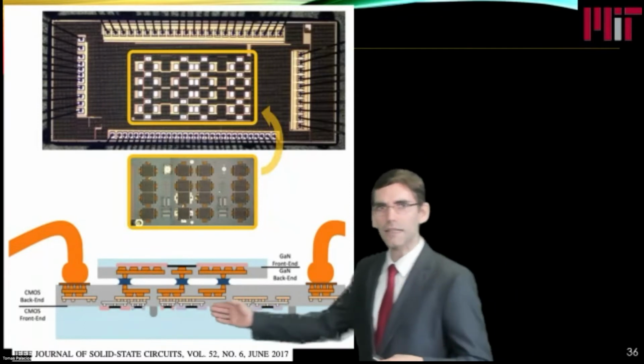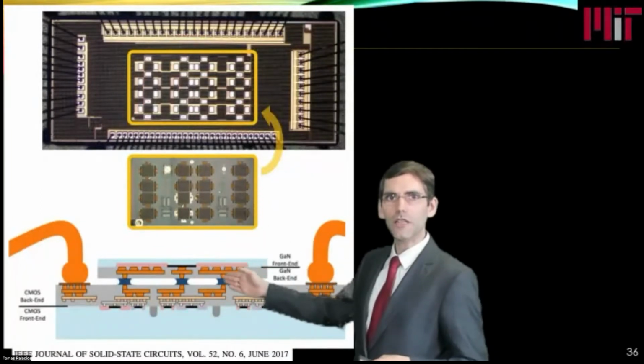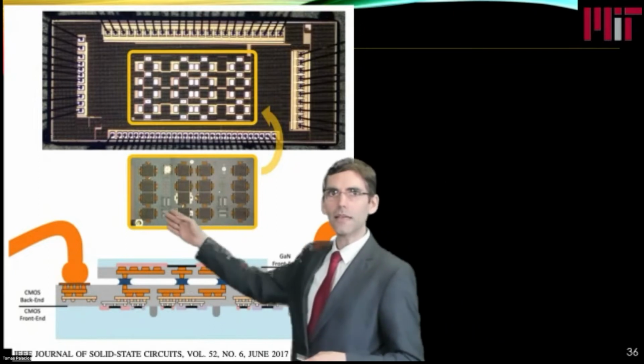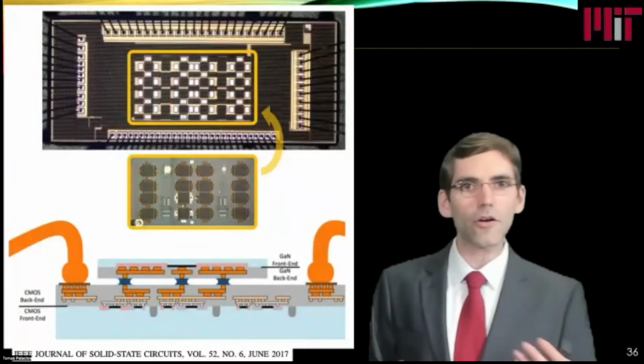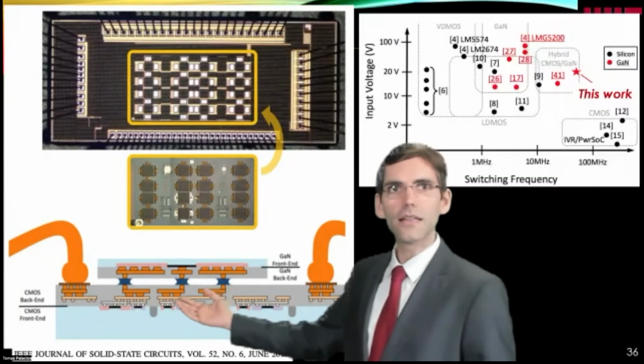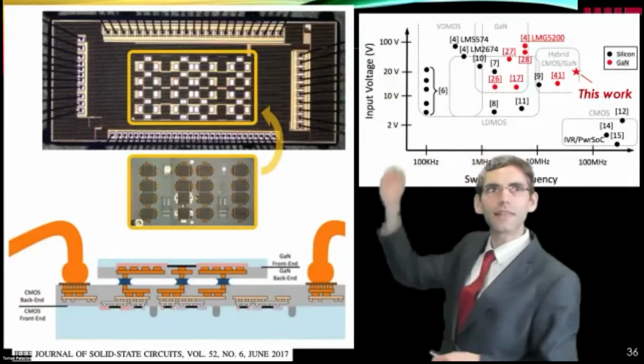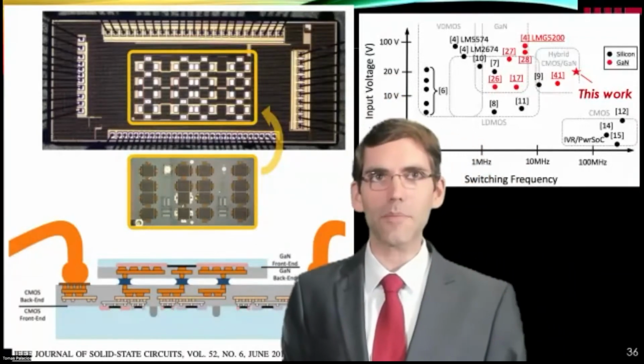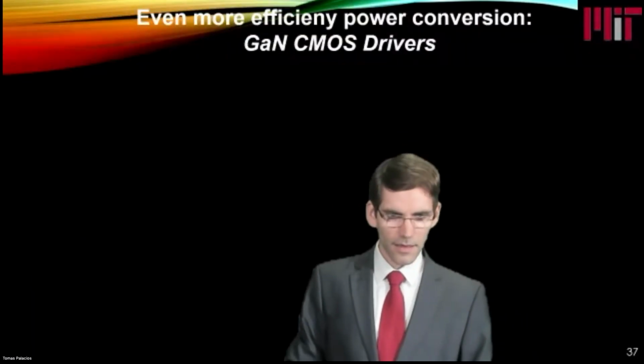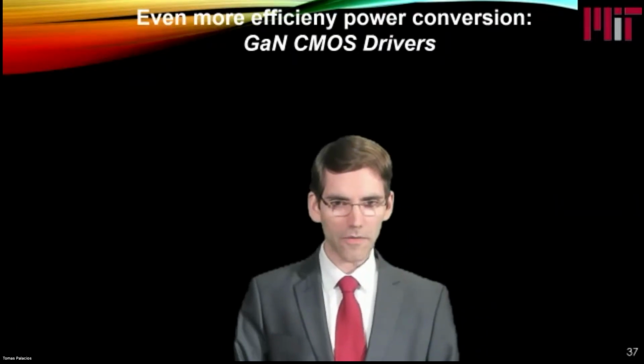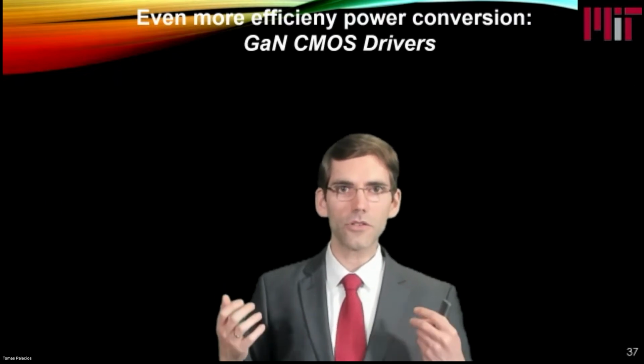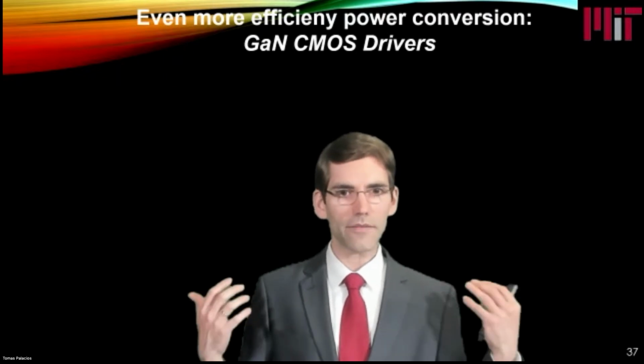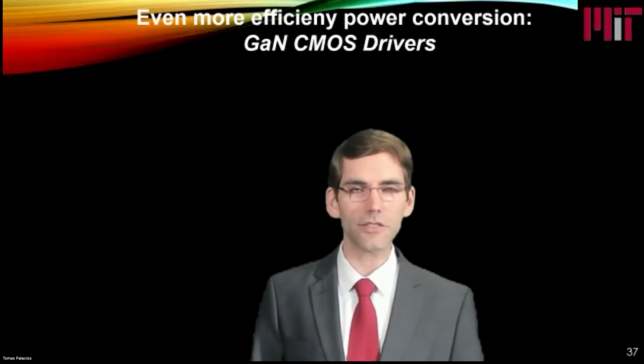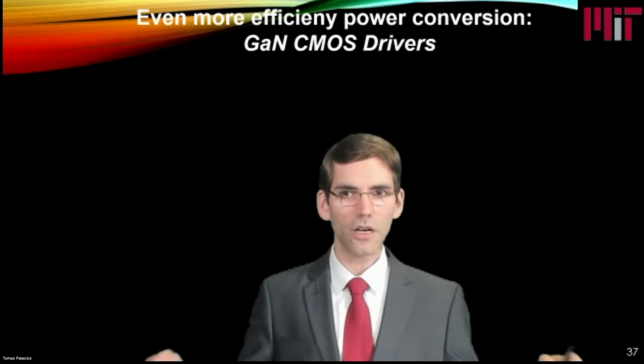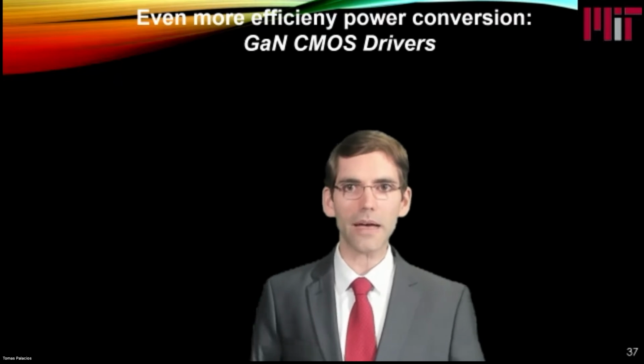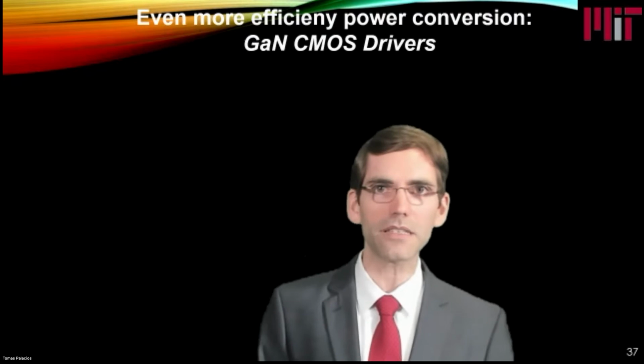For example, here we took a silicon microsystem and we flip chip bonded on top a gallium nitride chiplet with 16 different gallium nitride transistors that were doing the power conversion for the system. So we were introducing the voltage around 20 volts and then down converting it to whatever voltages we needed in the actual application. But if we really want to make an impact in power conversion, we need to be able to take advantage of truly CMOS circuitry. Everything we have done so far with gallium nitride has been based on N-type transistors. However, there is a huge body of literature that develops all kinds of circuits by using both P-type and N-type devices. And that is something that gallium nitride has not been able to leverage so far.